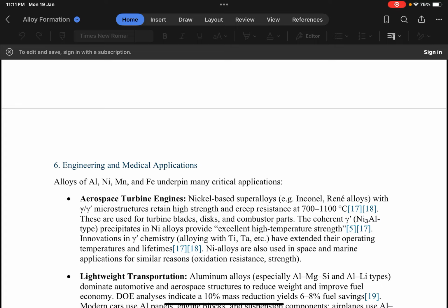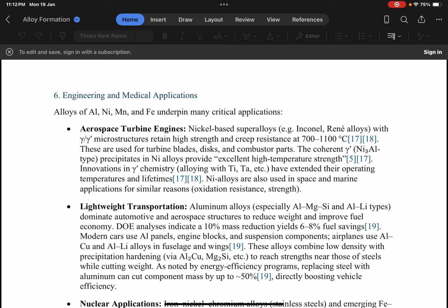Now, let's talk about the engineering and medical applications. Alloys of aluminium, nickel, manganese and iron underpin many critical applications. Number 1 is aerospace turbine engines. Nickel-based superalloys, for example, Inconel alloys with gamma-gamma prime microstructure, retain high strength and creep resistance at 700 to 1100 degrees Celsius. These are used for turbine blades, discs, and combustor parts. The coherent nickel-aluminium-type precipitates in nickel alloys provide excellent high-temperature strength. Innovations in gamma prime chemistry, along with titanium, tantalum, etc., have extended their operating temperatures and lifetimes. Nickel alloys are also used in space and marine applications for similar reasons: oxidation resistance and strength.